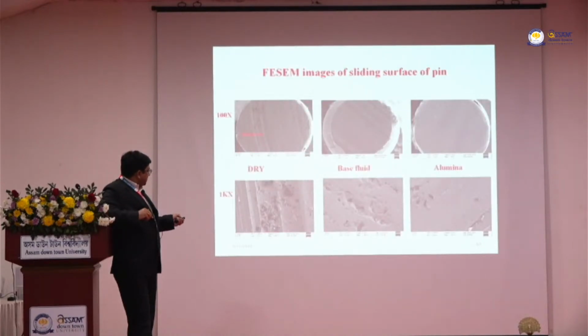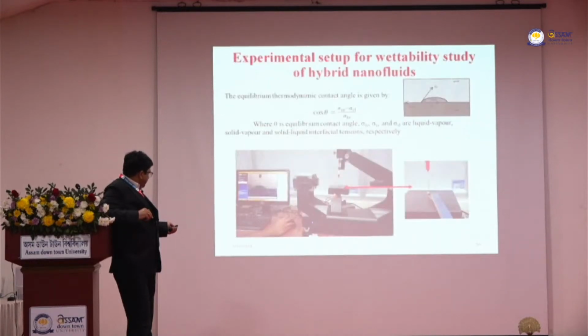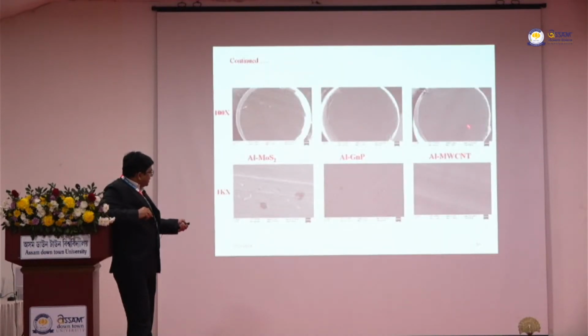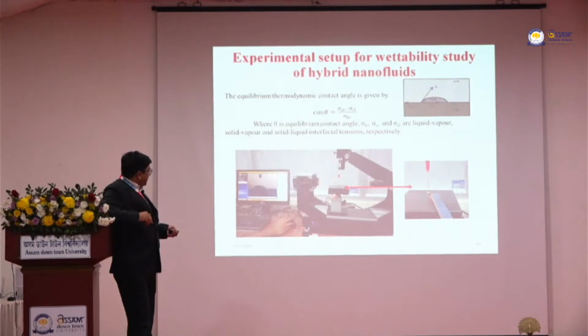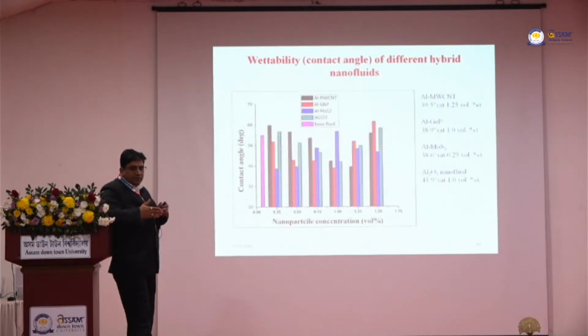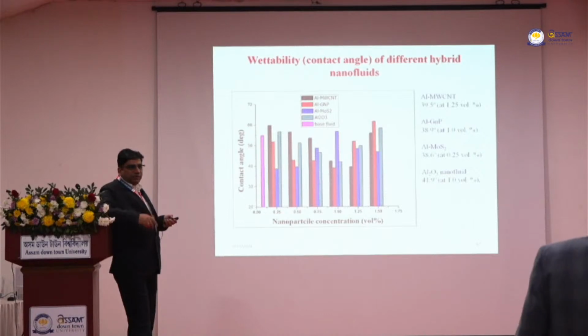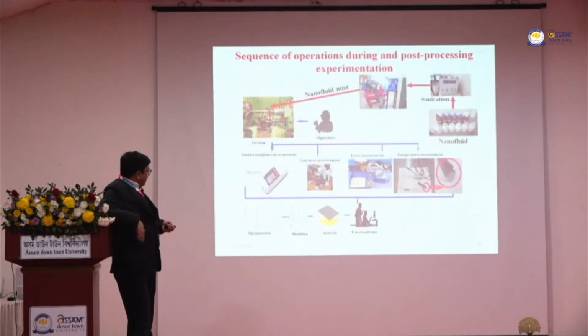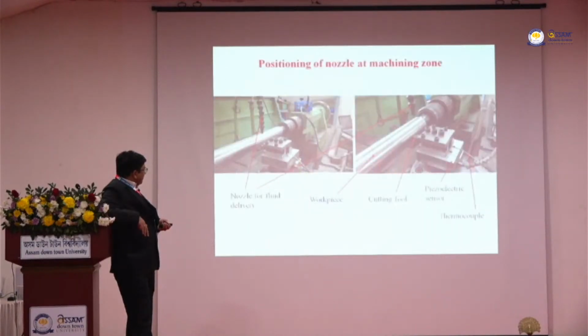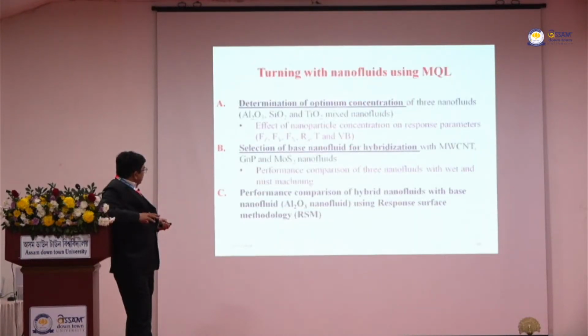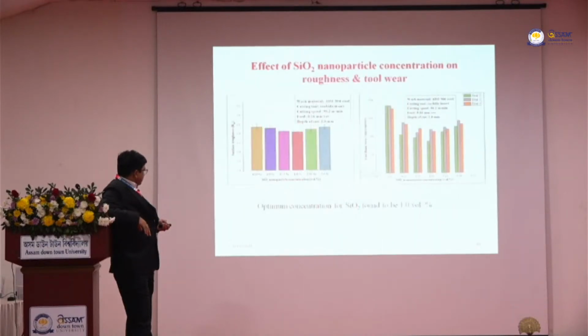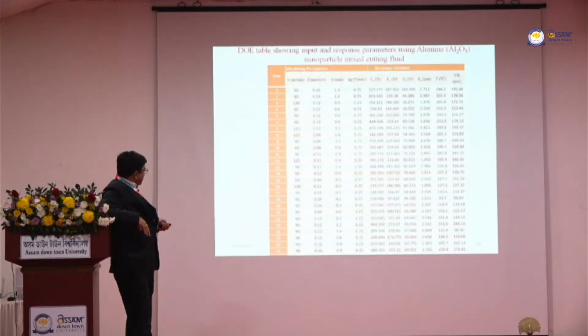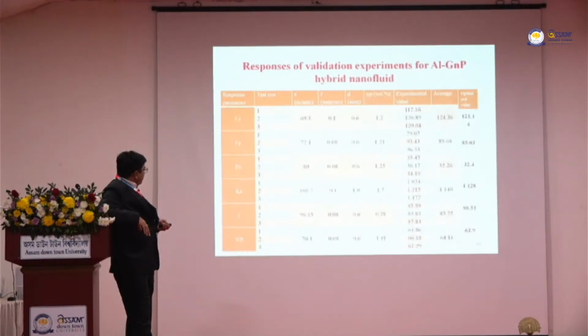Then we did FESEM. You can see if we compare the images, the dry machining, you can see how much roughness is there. But when you see the alumina MWCNT, you can see qualitatively better surface as compared to this. Then we did wettability with the goniometer. We found that the wettability is high as compared to the single nanoparticles. Then I will come to the conclusion. So this is the experimental setup. So let us come back to the conclusion. We did a lot of experiments. We optimized it. I am interested more in this.